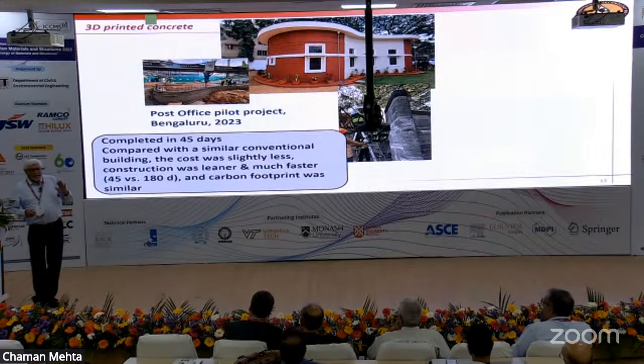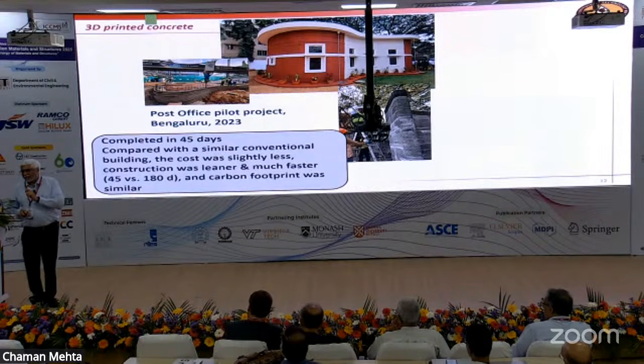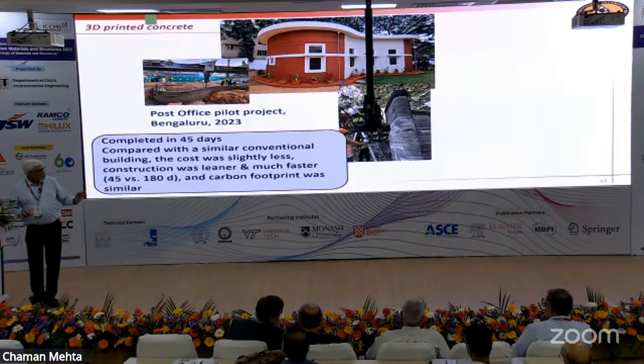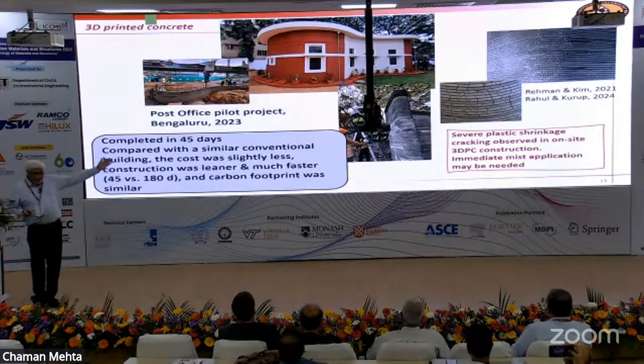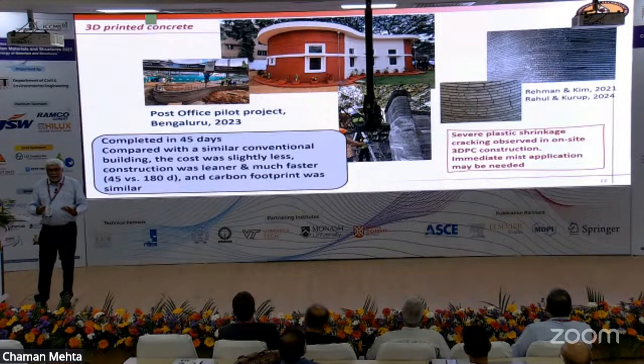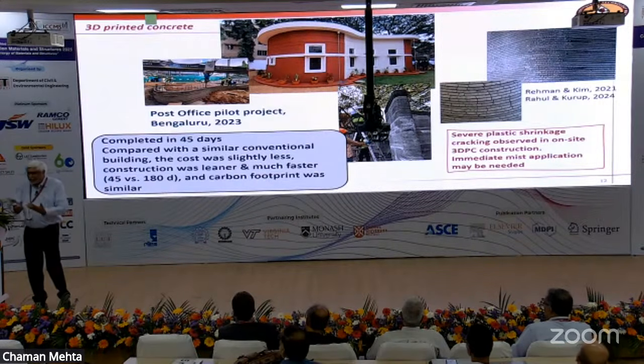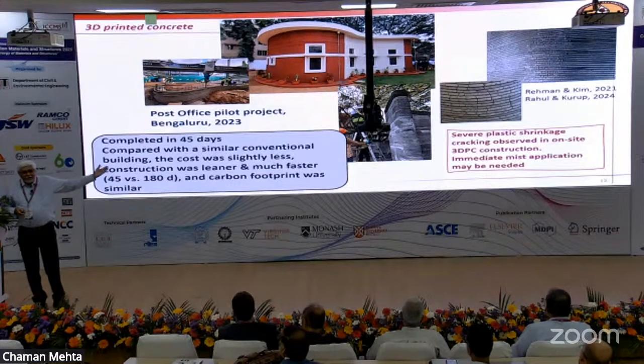3D printing is prone to severe plastic shrinkage cracking because you don't have aggregates. You have thin elements, very high surface area, very high cement content. On a hot day, a little bit of evaporation is going to give you a lot of cracking. Otherwise, the project is wonderful. But you can have cracks. There is work happening in IIT Tirupati where they are looking at cracks. You can see the cracks. Whenever concrete curves, there is a crack. Again, from the mechanics, you can understand there is hoop stress and so on. But we have to look at it.